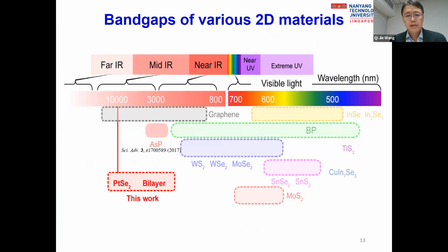Therefore, we look at the material possibilities that we can choose, and this shows a summary. For mid-infrared 2D materials, graphene is one choice. However, it is limited by its responsivity. Black phosphorus can cover up to around 3 micron. And recently, black arsenic phosphide was used to cover the wavelength range around 3 to 4 micron.